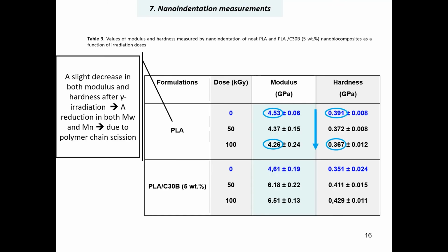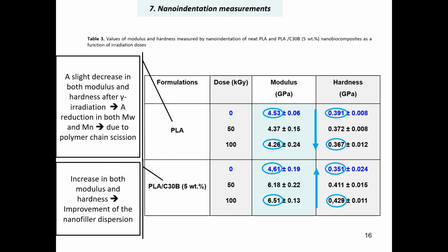Finally, the mechanical results obtained by nano-indentation measurements are shown in table 3, and we can see that for neat PLA there is a slight decrease in both modulus and hardness after gamma irradiation, which indicates the occurrence of a reduction in both weight average and number average molecular weight, which can be explained by the polymer chain scission. Whereas it is observed an increase in both modulus and hardness for the PLA-based nanocomposite after exposure to gamma irradiation, and this is probably due to the improvement of the nanofiller dispersion, which is consistent with the TEM data.